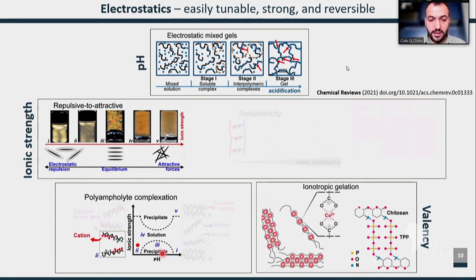And you can reach again a solution state, because I'm going to show in a minute that charges are always compensated, depending on the species that are compensating the charge. So this is what we call the salting-in. And as we go higher and higher in ionic strength and we put more salt, then there is the salting out. The electrical double layer is so thin that it barely exists. And then Van der Waals forces start to take place as attractive and not repulsive, okay?